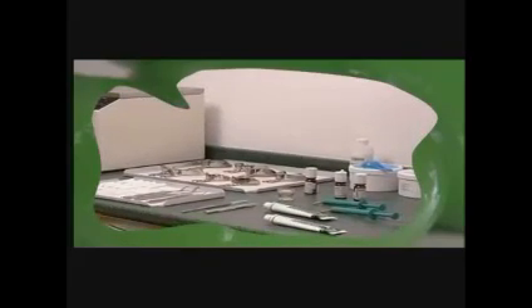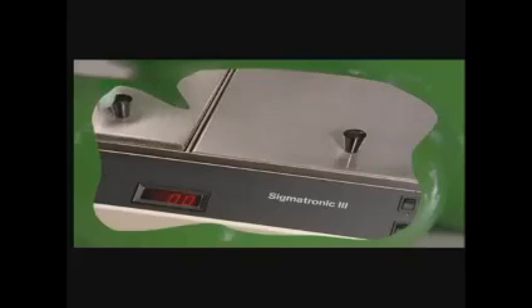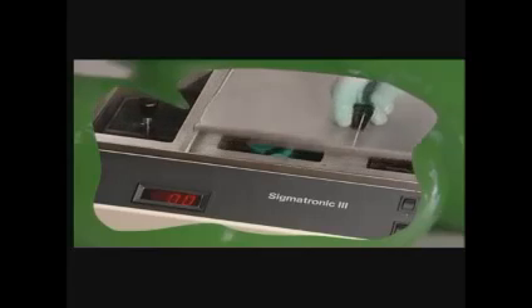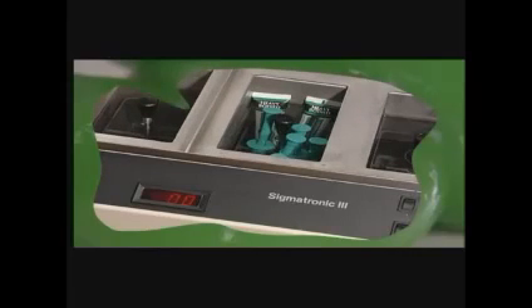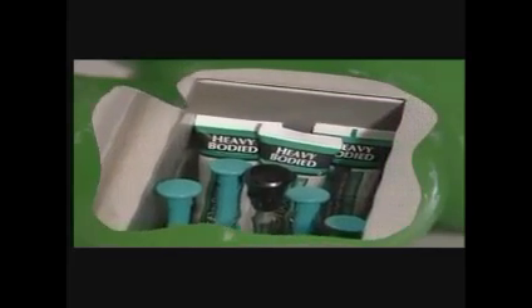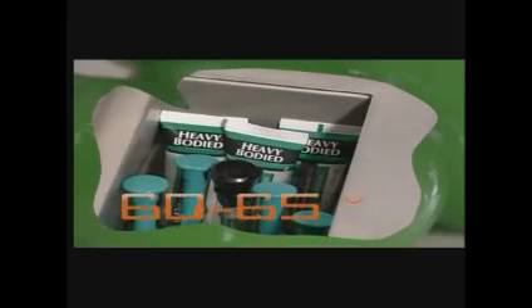A lot of work goes into a hydrocolloid impression. Among other things, 3 separate water baths with different temperatures are used for material preparation. They comprise a boiling bath at 100 degrees Celsius, a storage bath of 60 to 65 degrees Celsius, and a tempering bath with a temperature of 42 to 48 degrees Celsius.